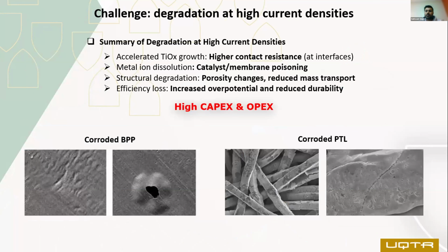Under acidic operating conditions, titanium forms an oxide layer on the surface very easily, and that oxide layer protects the metal from further corrosion, but also hinders the cell performance. How? Because this titanium oxide layer is less conductive, increases the contact resistance, and reflects higher operating voltage, eventually increasing the operating expenditure of the cell. It means after the titanium oxide formation, now we have to burn more power to produce the same amount of hydrogen gas. And you can see this is how titanium bipolar plates and the PTLs look after the corrosion during long-term operations. Actually, this is the main issue of the electrolyzer, specifically PEM water electrolyzer, making it a highly costly technology to adopt commercially.